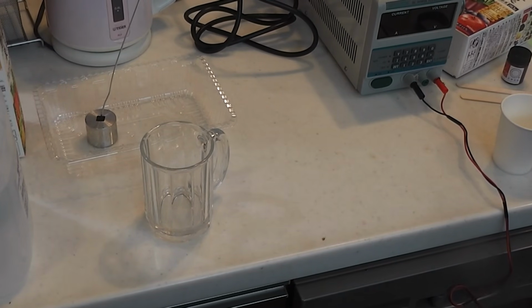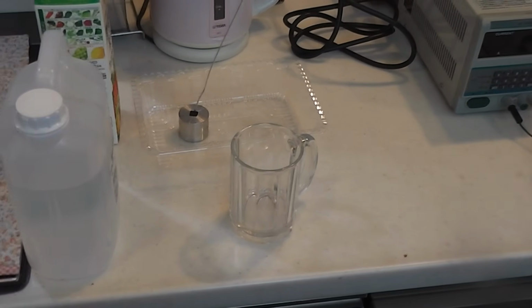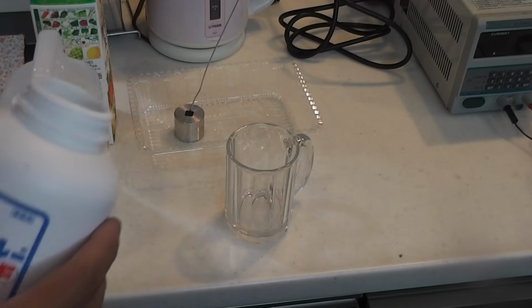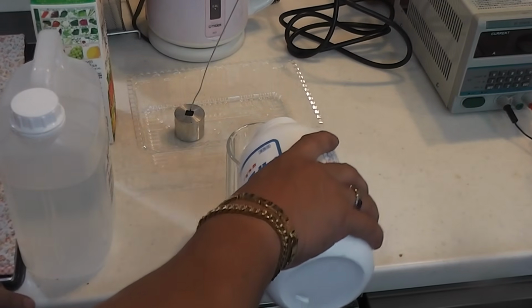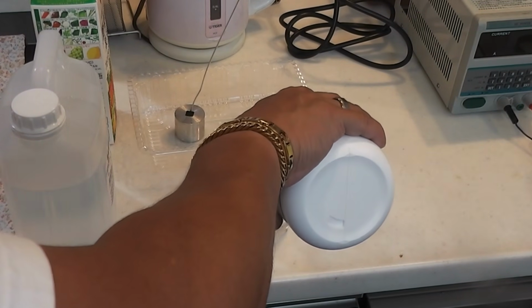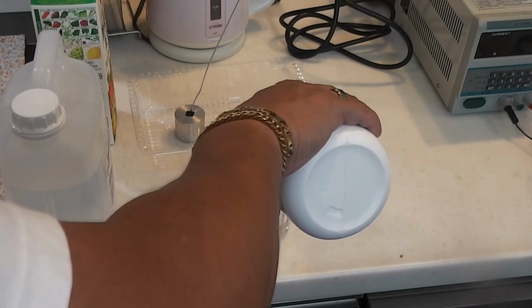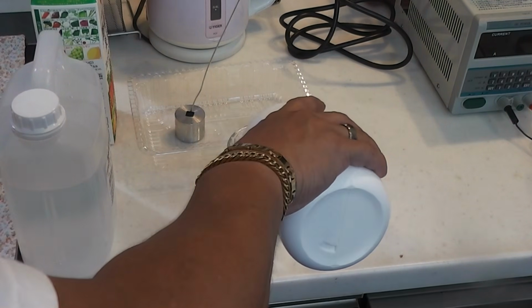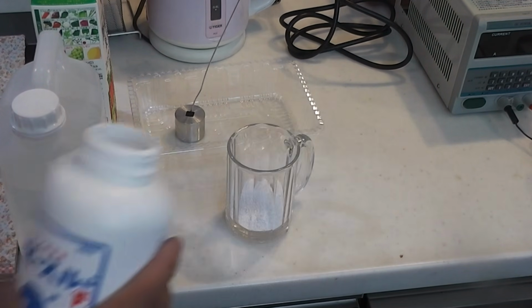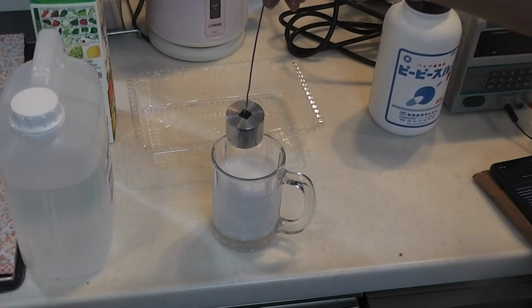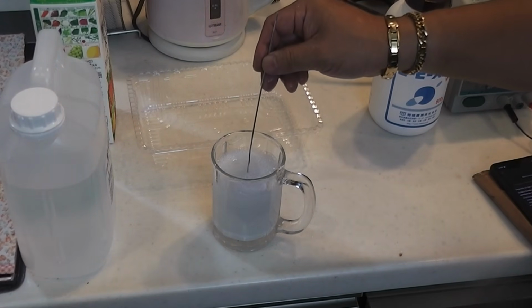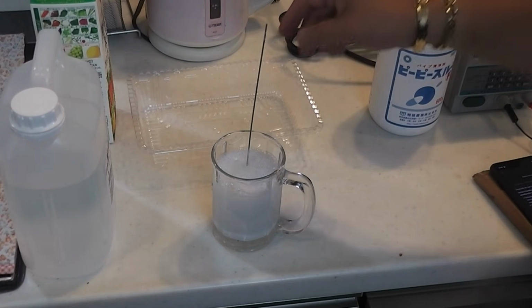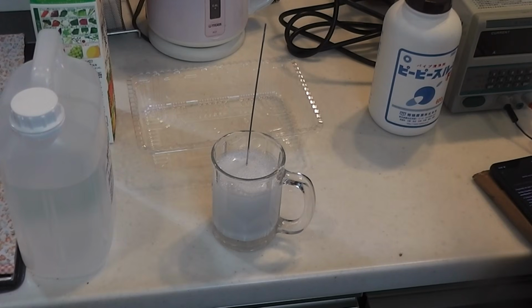One small change during the process makes a surprisingly big difference in the final finish. Let's get started. The first step is surface preparation. Before anodizing, the aluminium must be perfectly clean. I begin by preparing a caustic soda solution. The aluminium socket is immersed in the solution to remove the existing oxide layer, along with any grease, fingerprints, machining residue, or other contaminants. This step creates a fresh, uniform aluminium surface.